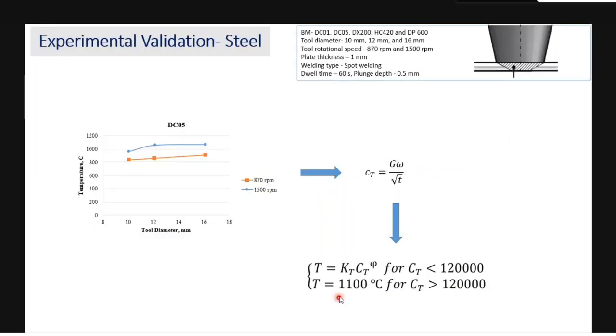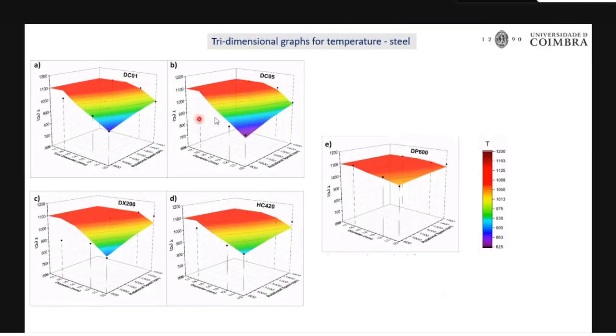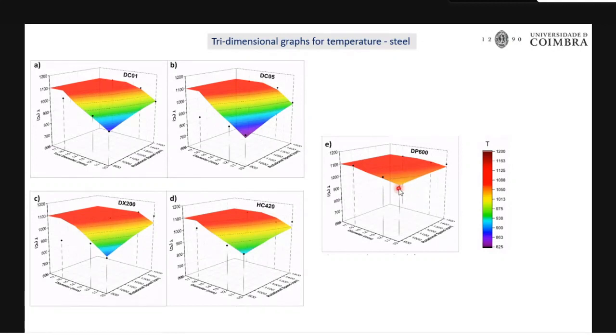And here the maximum solid state welding temperature of the steel identified is 1100. Here you can see that the dotted lines are the experimental values, and the surface plot is the predicted values. It is showing a very good improvement. And here you can see that DP600 is a high strength material, so it offers higher temperatures because of high flow resistance, so which were also.